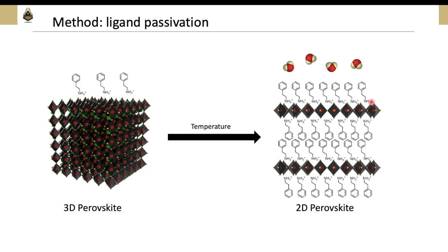2D perovskites have superior stability and water resistance compared to 3D because the ligands on top protect the perovskite from moisture ingression. However, if the 2D perovskite layer is too thick, these bulky organic tail groups can block charge transportation and therefore reduce the device performance. My task is to control the type and thickness of different 2D perovskite passivating layers to tune the surface optical electronic properties and stabilize the surface.